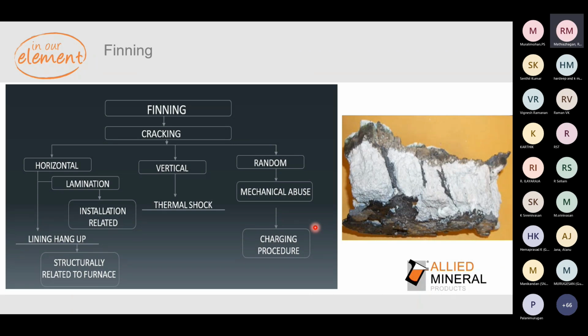So coming to finning. Finning is metal penetration in the lining. It's because of cracking. Cracking can be either horizontal, vertical, or random. When we talk about horizontal, these are hard to seal, and it's majorly because of lamination or the lining getting hung up. Lamination is installation related. For example, you do a manual ramming, you fork it, do a compaction, and then before forking, if you add this refractory, there's always a lamination. It can be easily identified when you break the lining, because in the complete circumference of the furnace, the metal will be sitting like a washer. So it's called lamination.